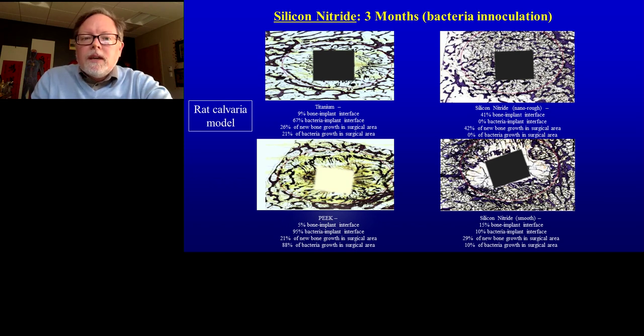Titanium, which is pictured just above PEEK, did a little bit better, but you can still see a lot of yellow, particularly on the right side of this particular slide. So that yellow, again, signs of bacteria. When we quantified it, we got on average 67% of the titanium surface was covered in bacteria. When we moved to silicon nitride, changing chemistry already improved our ability to inhibit bacteria. So on the bottom right corner, you can see silicon nitride that's smooth. So this was the starting material made by Amedica. Immediately, there was a reduction in bacteria growth. So there's something unique about the silicon nitride chemistry, the silicon nitride surface energy that reduces bacteria attachment and growth.